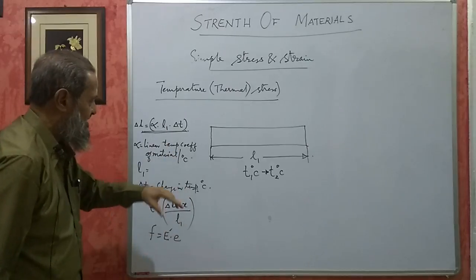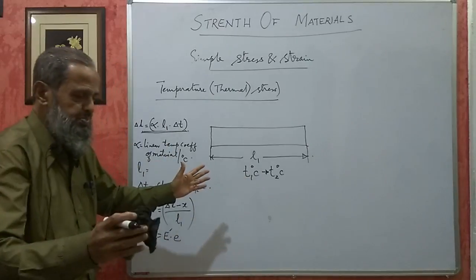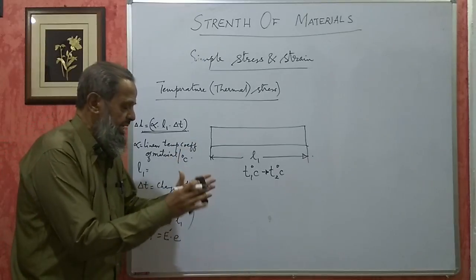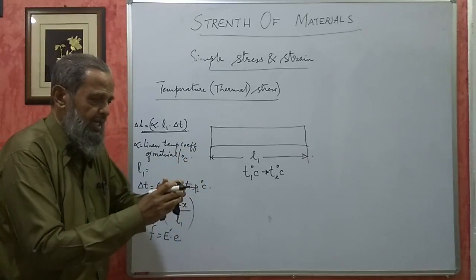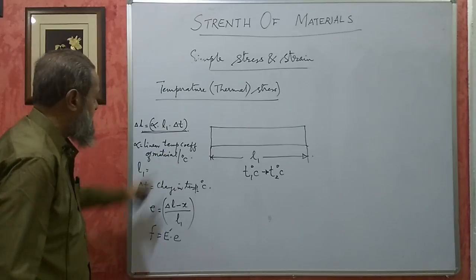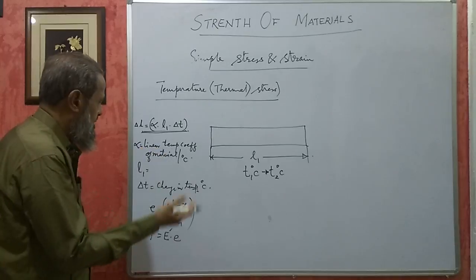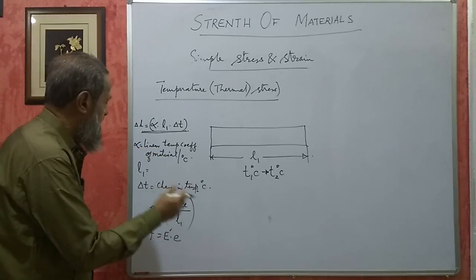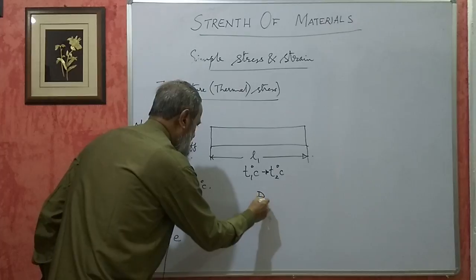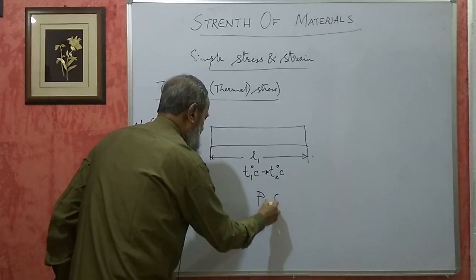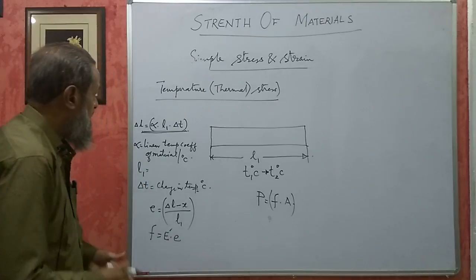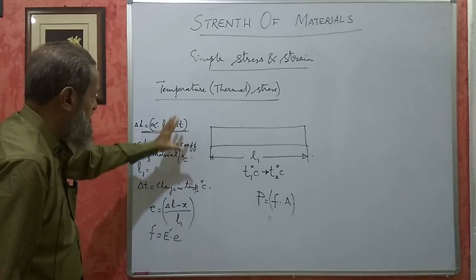The nature of this stress will be either tensile or compressive. If we are heating it and it wants to expand but we don't allow it, then it is compressive. If we are cooling it and it wants to contract but we don't allow that contraction, then tensile stress is developed. The axial load to which it is subjected will be stress × area of cross section.